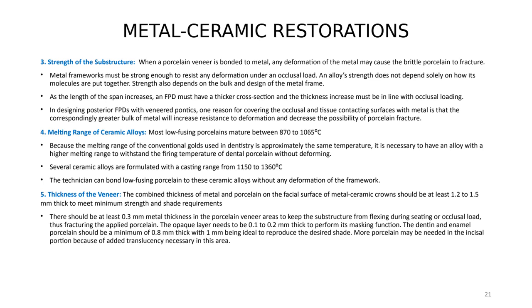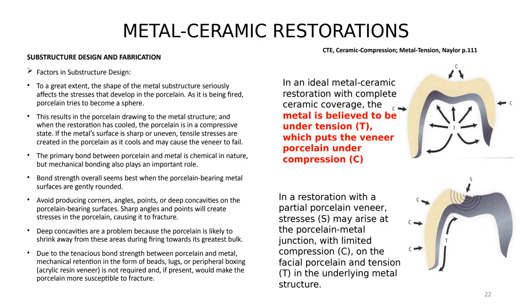The opaque layer needs to be 0.1 to 0.2 millimeter thick to perform its masking function. The dentin and enamel porcelain should be a minimum 0.8 thick, with 1 millimeter being ideal to reproduce the desired shade. More porcelain might be needed in the incisal portion because of added translucency necessary in that area.